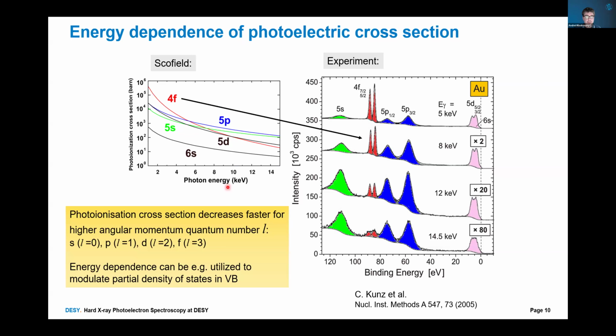So, of course, going to high excitation energies, and in this case higher kinetic energies of photoelectrons, is not for free. We have to count on strongly reduced intensity, because the photoionization cross-section of the electrons decreases with the excitation energy, and it also decreases faster for higher angular momentum quantum number. This means that if for lower photon energies the spectra are dominated by F and P lines, in hard X-ray excitation the photoionization cross-section drops down for F lines, and the intensity of the spectra is dominated by S